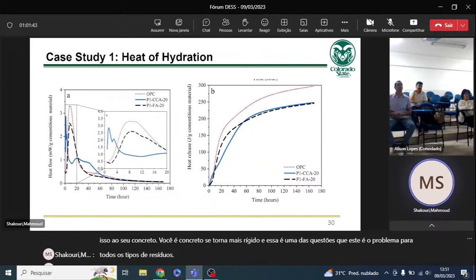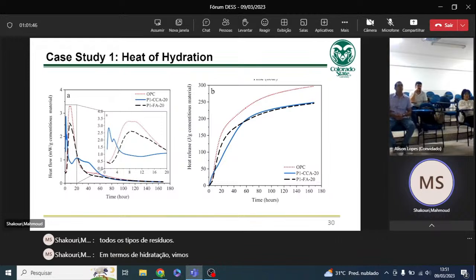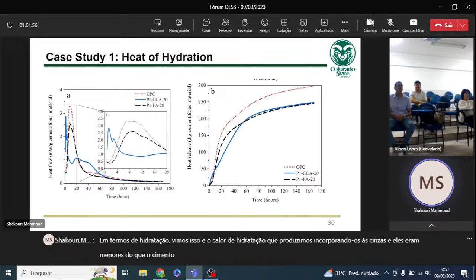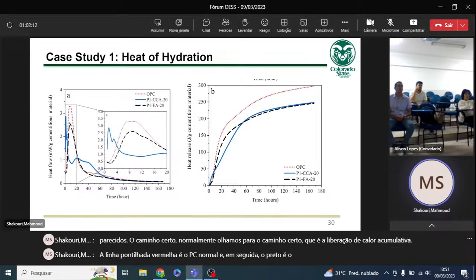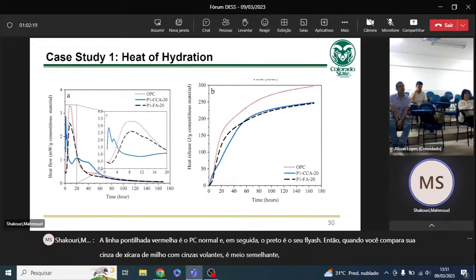In terms of hydration, we saw that the heat of hydration produced by incorporating these two ashes was lower than the normal cement. On the right side, we typically look at the cumulative heat release. The red dotted line is the normal OPC, and the black one is your fly ash. So when you compare your corn cob ash with fly ash, it's similar, but it has a lower heat of hydration at the initial stages. So what it means is that it takes more time for your concrete to reach that stiffness or hardness.